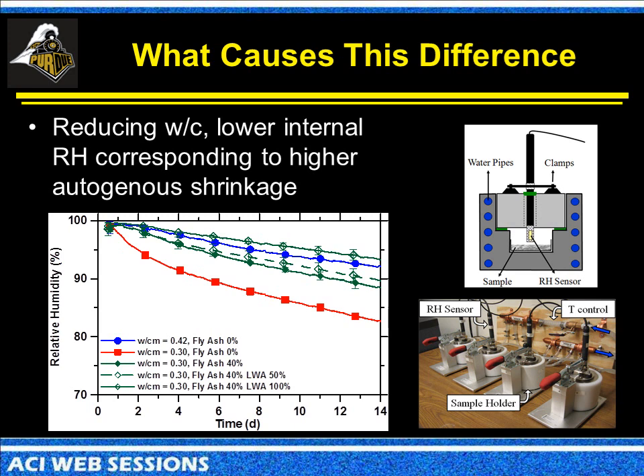The relative humidity as a function of time is essentially telling you an indication of how much pressure is inside of the pore fluid. So here we can relate the humidity that's taking place inside of the system, or the equivalent internal humidity, with how much stress is being put on the matrix to cause this concrete to want to shrink without the loss of moisture to the outside. Again, if we've got just our 0.42 water-cement ratio, we see a lot higher relative humidity inside of our concrete, a lot less autogenous shrinkage taking place. 0.3, we see more autogenous shrinkage taking place. And then we've got here the dark symbols being the case where we're looking at the fly ash. Again, it's reacting a little bit more slowly.